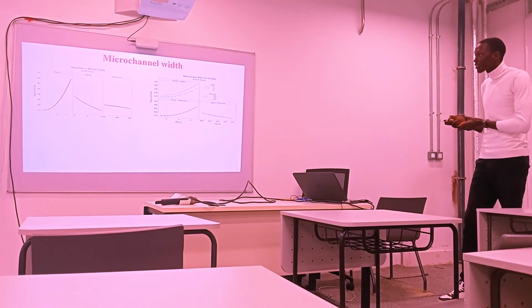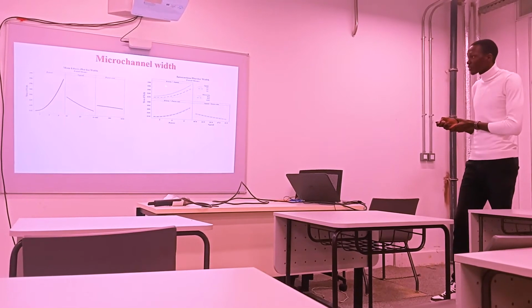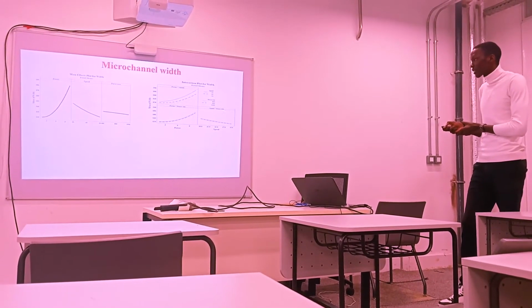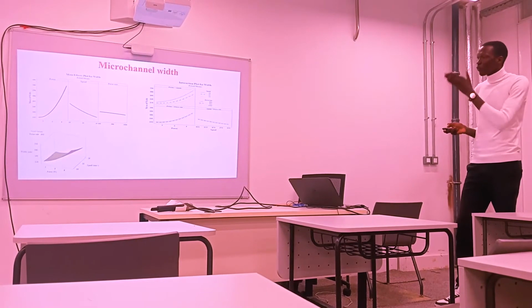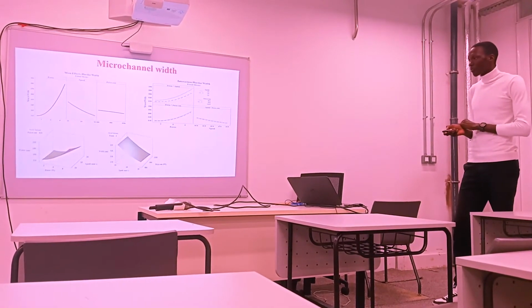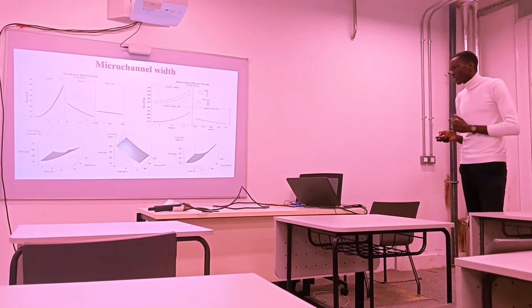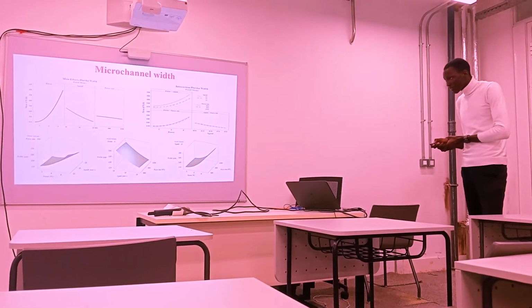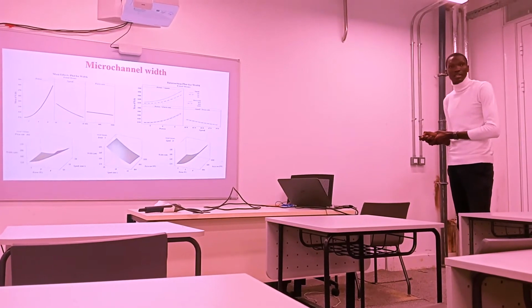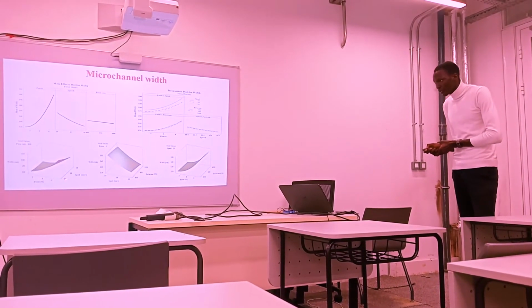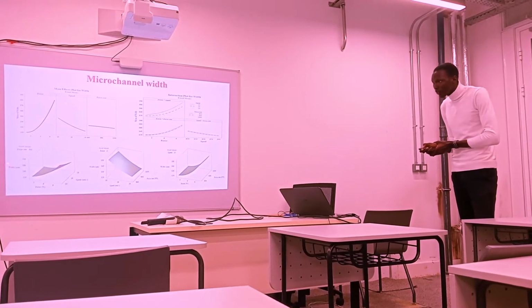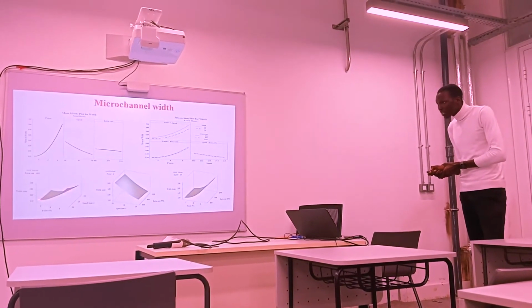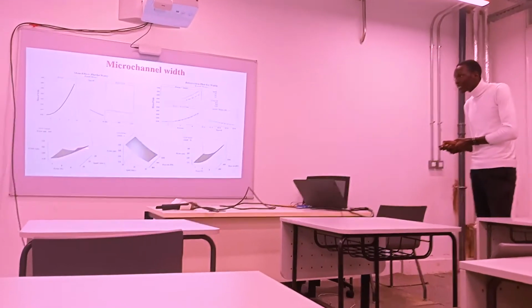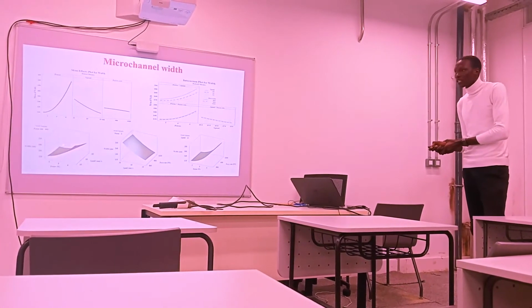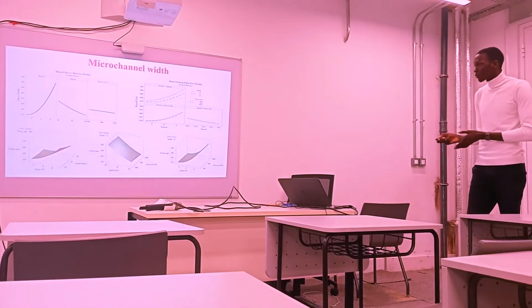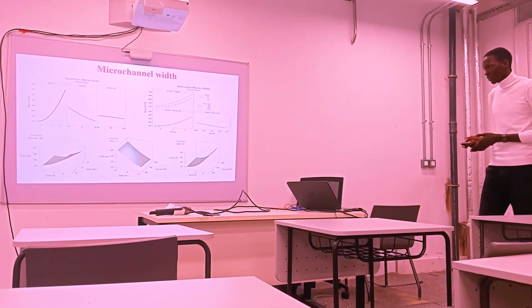This is the interaction plot for the width. This is the interaction of power and speed, power and pulse rate, power, speed and pulse rate. Then we produced surface plots from Minitab 19.1, and these figures, the surface plots, communicate the same thing as this figure. For example, this is power and channel width. You can see that the width increases with the increase in power, but decreases with the increase in speed. The same thing applies to these other two plots.